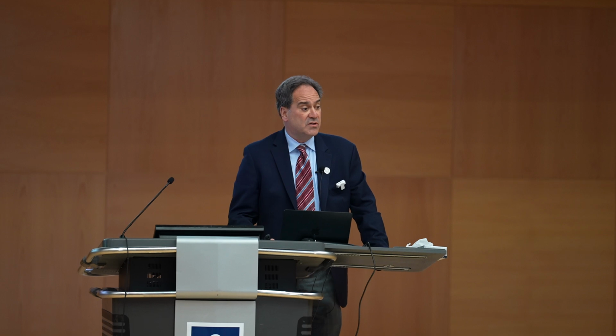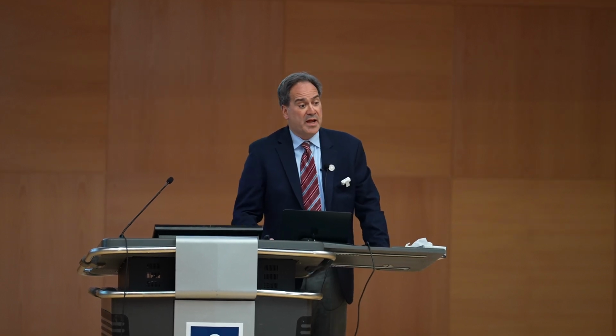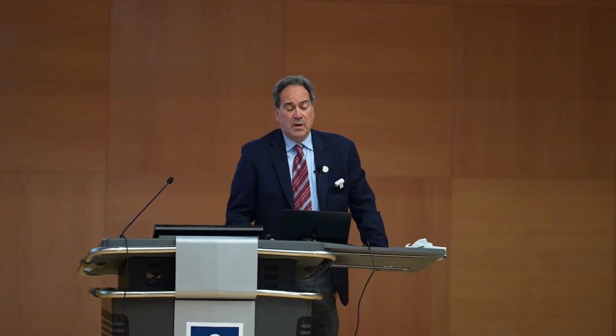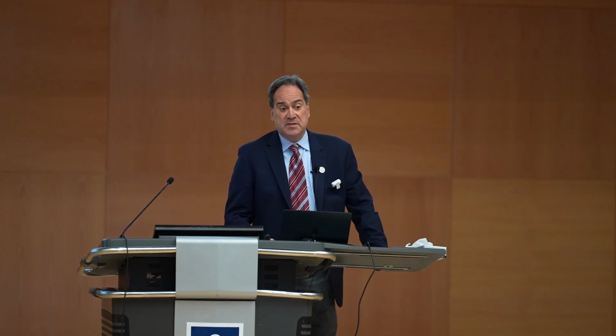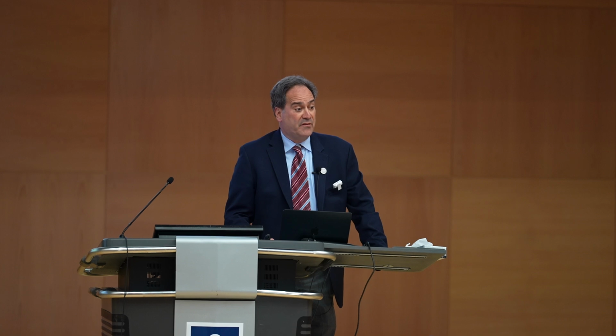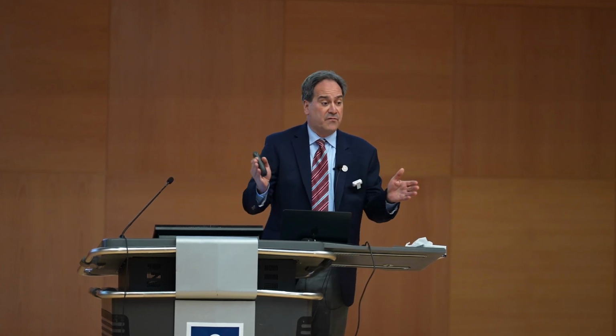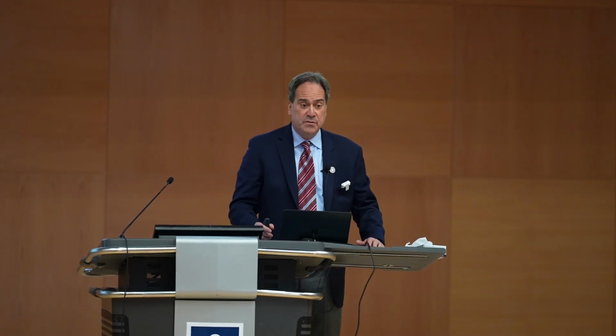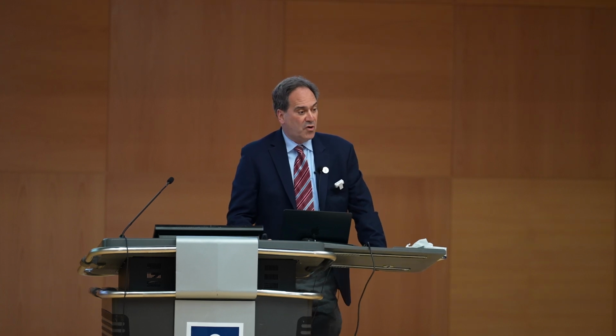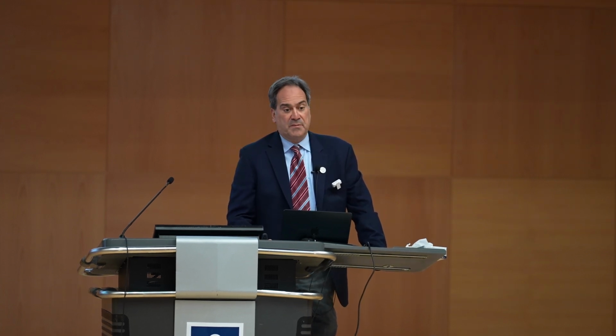And we had one in a facility, and we began to study surfaces in a variety of different ways, and we discovered something very interesting, and that was that when you run an AFM in air, water will naturally collect at the point of contact and form a meniscus. That's called the capillary effect. That's the thermodynamic sink for water in the environment to move to. And that's usually viewed as a problem in scanning probe microscopy.